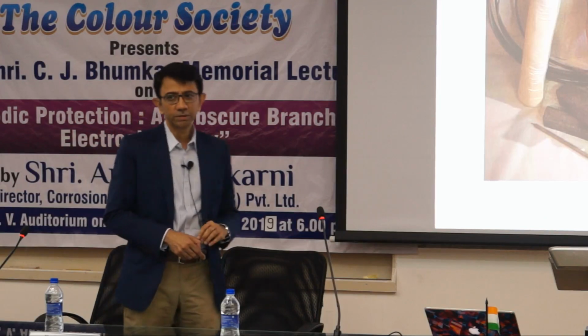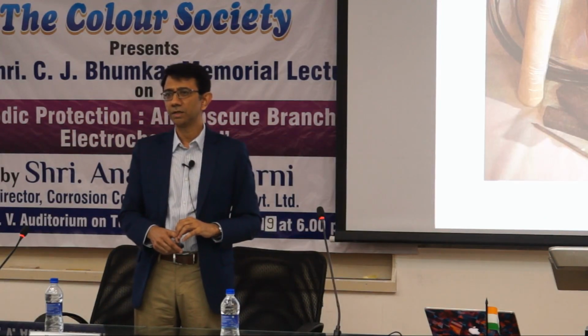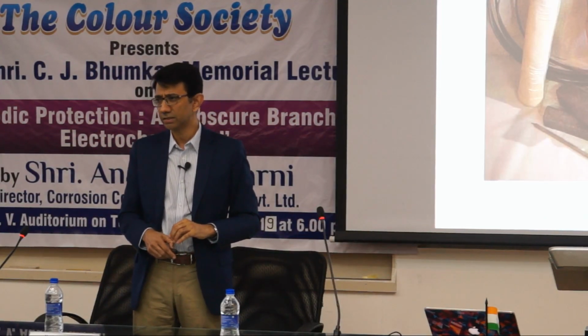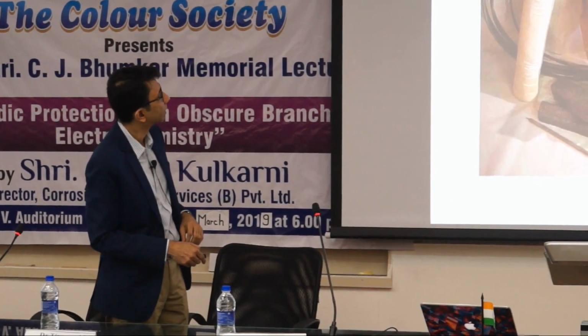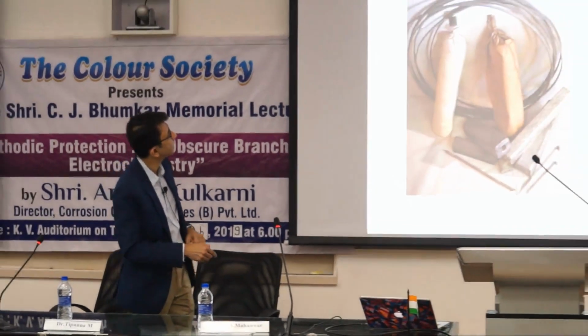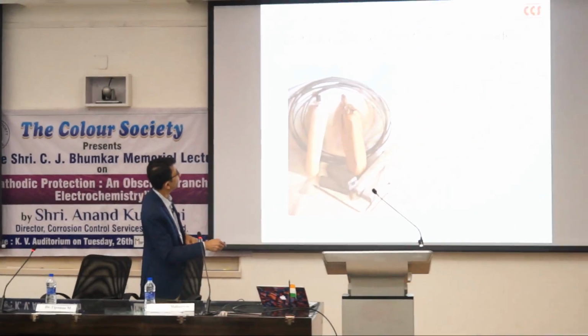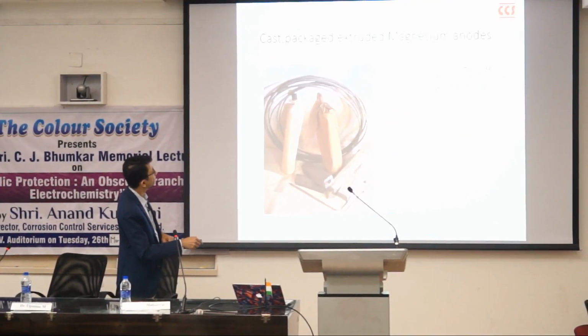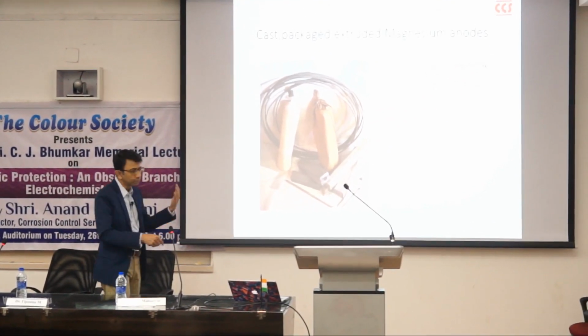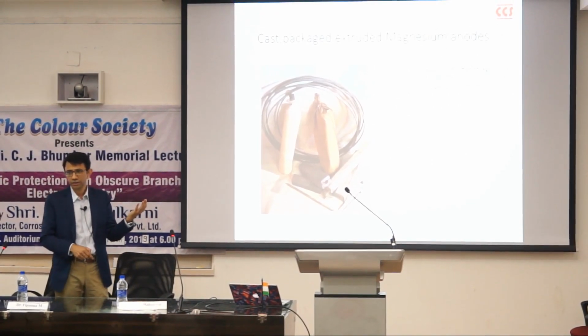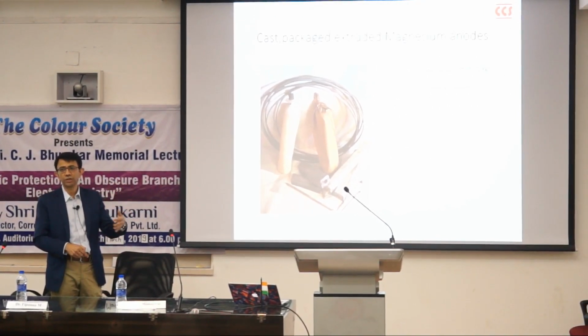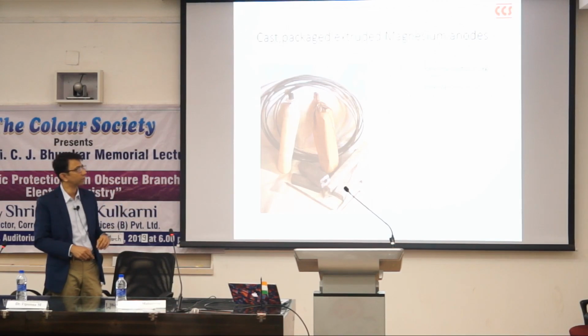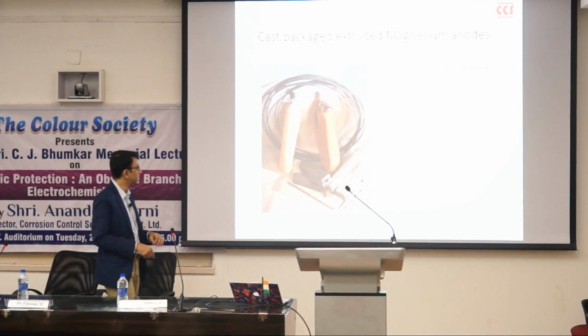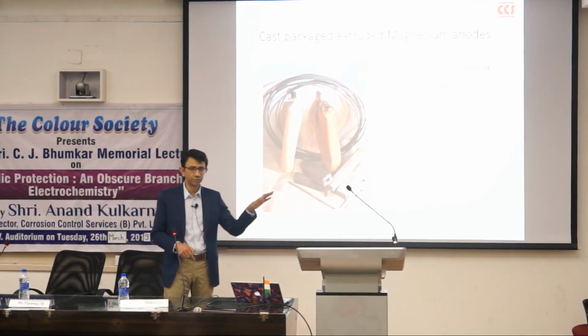We saw in the first EMF series slide that the more electronegative a metal, the more active it is. So, in order that it exhibits this kind of potential, it has to be very pure. Then we come to magnesium. We find that magnesium is far more versatile than zinc because of its electrochemical potential. This is a mistake here, I am sorry. This should be minus 1.5 volts. So, it is more electronegative compared to zinc, and so obviously the constraint of high soil resistivity is taken care of. Magnesium is another great anode when it comes to all types of soil resistivity.